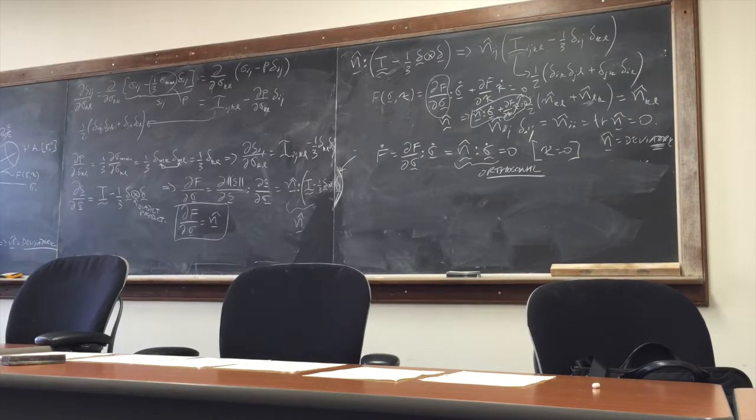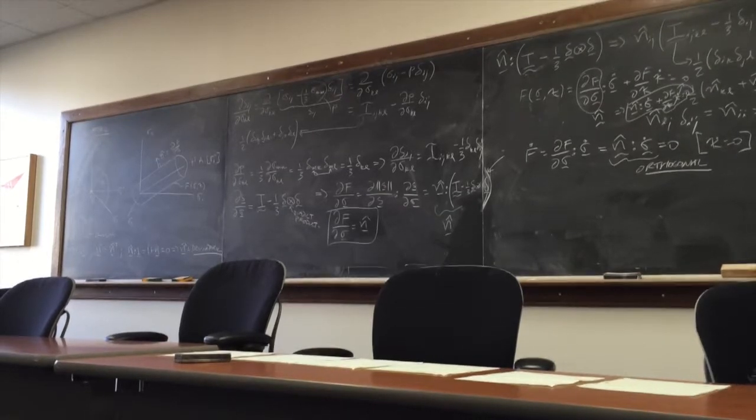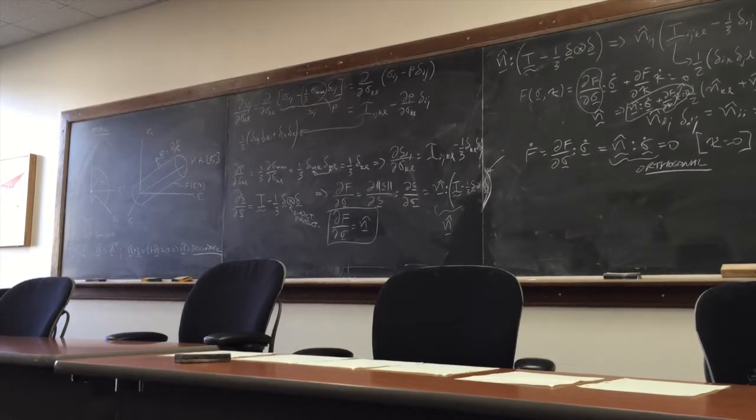So that means that you can only allow for increments in stress that are on the surface or along the surface of the cylinder, right? All of your sigma dots need to be tangent to the cylinder. They cannot have any component in the direction normal to the cylinder. Okay, so in the case of perfect plasticity, meaning that your radius cannot expand or contract, your sigma is limited to living in an infinite cylinder, right? And it's limited to only taking new values along the surface of that cylinder. But it can never go outside. It can come back in and become elastic again, but if it wants to continue to be plastic, its only potential increments are tangent to the cylinder. Okay?